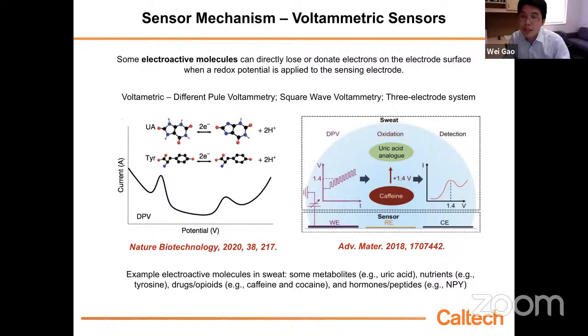For example, if you do a DPV scan in human sweat, you see two significant peaks. The first one belongs to uric acid. This is using a carbon electrode. Uric acid, which is metabolized, can be oxidized at around 0.4 volt. The current peak height corresponds to the concentration of uric acid. In general, if we want to detect some drugs such as caffeine, caffeine can be oxidized at high voltage, at around 1.4 on a carbon electrode. The peak height obtained here has a linear relation with the caffeine concentration.